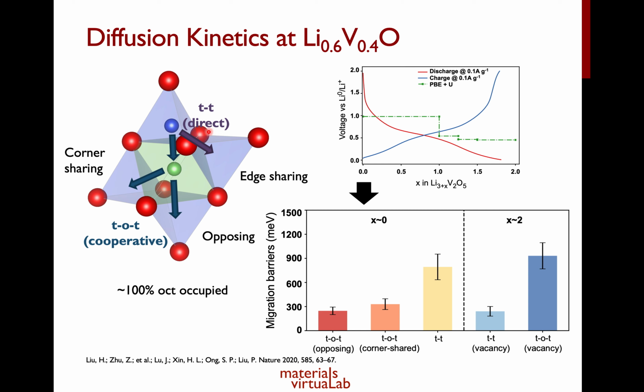Now another mechanism that we investigated is what is known as the TOT cooperative mechanism. In this mechanism, basically what happens is that we have lithium from this tetrahedral site going to this octahedral site, but at the same time, the lithium in this octahedral site now hops into one of the neighboring tetrahedral sites. So in other words, this is a two-lithium process. You basically have both lithium moving at once.